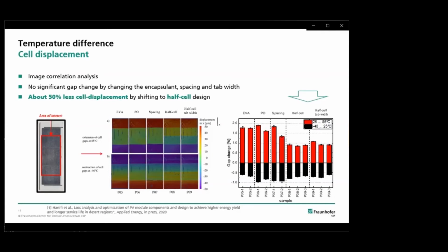And what you can see here is that there was no significant change when we changed the encapsulations from EVA to polyolefin, and also changing the spacing had not a detrimental impact. But there was about 50% less cell displacement by shifting from full cell to half cell design, with barely any changes with the tap width again. So half cell modules could really reduce the issue of interconnector breakage, which is a nice result.